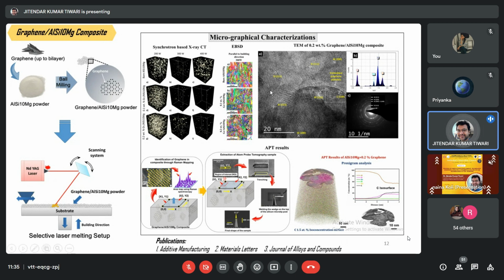So these are basically the characterization techniques which I have already used, and it is very important to know these characterization techniques when you are going to study the material, because if you don't know the material, you cannot use it. So a very innovative result we found from this research: when we add graphene into the metal and fuse it with the laser, people say that graphene can react with the aluminum and form aluminum carbide, or it can get evaporated, or it can get damaged.